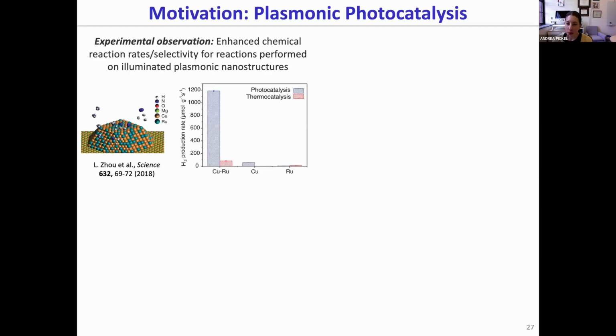So many experimental demonstrations have shown that chemical reactions can be strongly enhanced when the reactions are performed on the surfaces of illuminated plasmonic nanostructures, which is known as plasmonic photocatalysis. And specifically, it's frequently been observed that you can enhance the reaction rates or selectivity relative to traditional thermal catalysis processes that involve bulk heating of large reactors. And so this has led to a number of compelling potential applications.